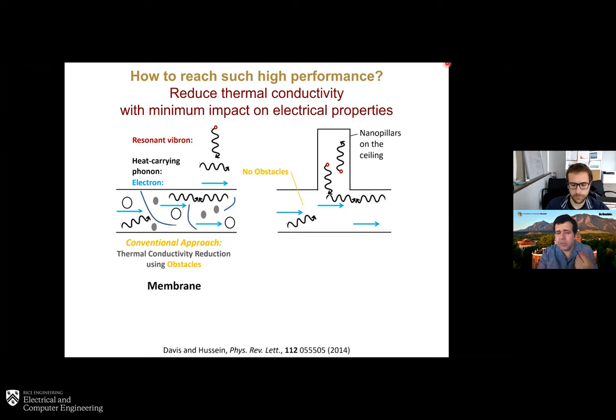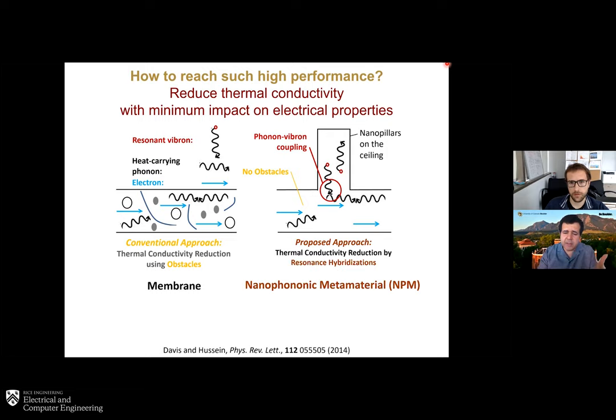What these vibrons will do is couple with the phonons. It's the same structure, it's contiguous. So in the steady state, or even in a transient state, you will continuously find phonon-vibron coupling taking place between those two elements. That's the key phenomenon that we utilize to reduce the thermal conductivity. That's what we call an NPM. I'm now going to go through a step-by-step description of how we go about the modeling to show this phenomenon and how it affects the thermal conductivity. Later on, I'll also touch on the electronic properties, as well as some preliminary experimental results to validate these effects.